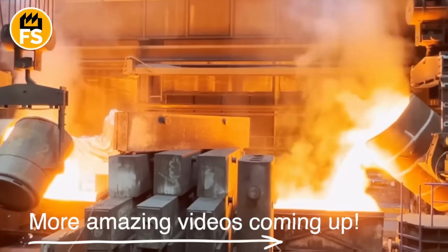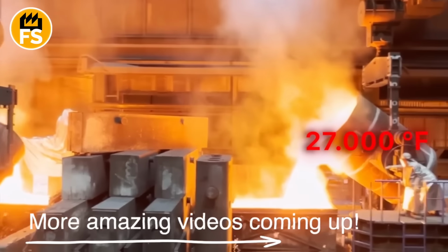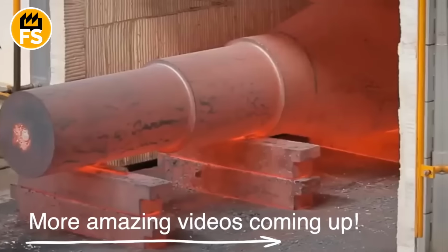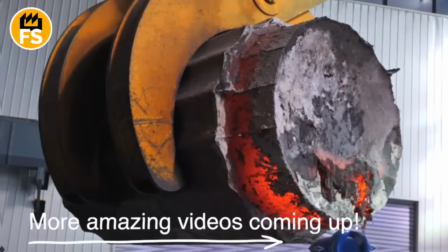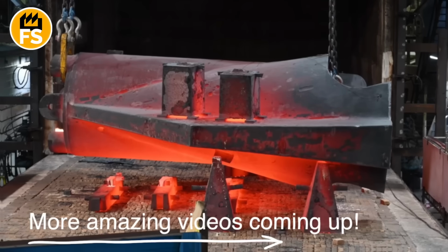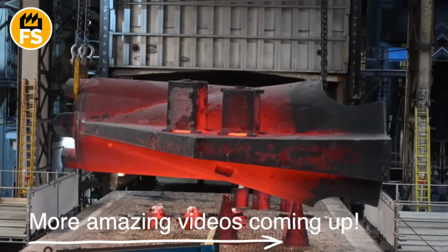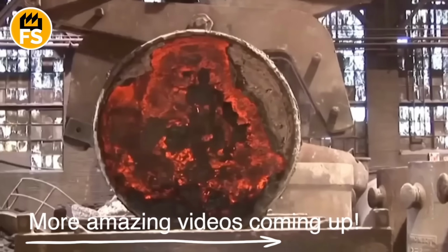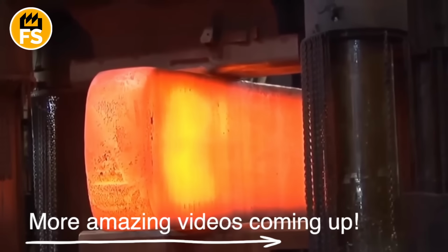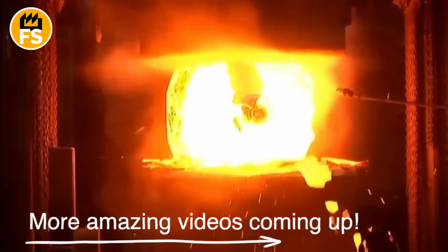Immediately after pouring the molten metal, which can exceed 2,700 degrees Fahrenheit, time becomes the most critical factor in this process. Unlike small ingots that can cool quickly, a steel giant weighing hundreds of tons cannot be cooled rapidly. If cooling happens too fast, it leads to massive internal stresses, cracks, and structural defects, because the outer layer solidifies while the steel inside is still liquid.